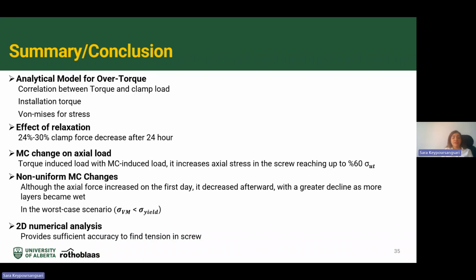Finally, I should say that based on this research, we found that the analytical model can give us a good estimation and can predict the relation between the torque and the clamp force. Also, by using the analytical model, we can find the installation torque and the threaded torque. And by finding these parameters, we can find the stress on self-tapping screws by using the von Mises theory. Also, as I mentioned, the relaxation phase has an effect on the clamp force, with around 25 to 30% of clamp force decrease 24 hours after installation. Also, we found that the combination of the torque and moisture content change can increase the axial stress in self-tapping screws up to 60% of the ultimate tensile strength of self-tapping screws.